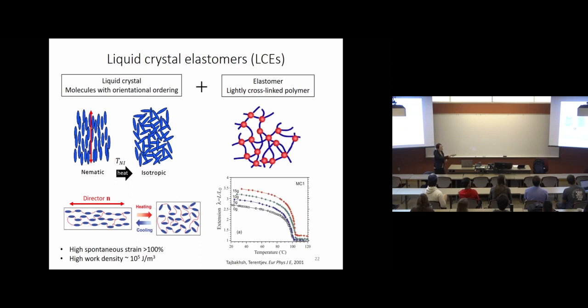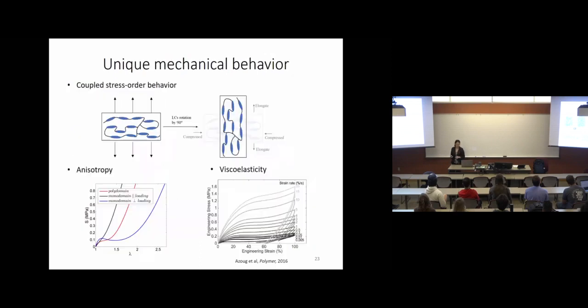So typically, this shape change can be larger than 100% once you just heat a sample. And moreover, this process is reversible. Once you cool it back, it can recover its original shape. Therefore, liquid crystal elastomers can produce high work density, and are typically considered a very ideal artificial muscle for soft machines.